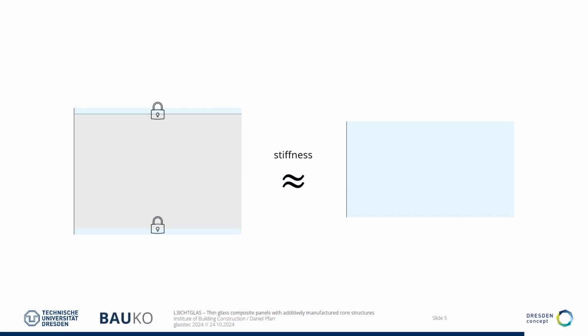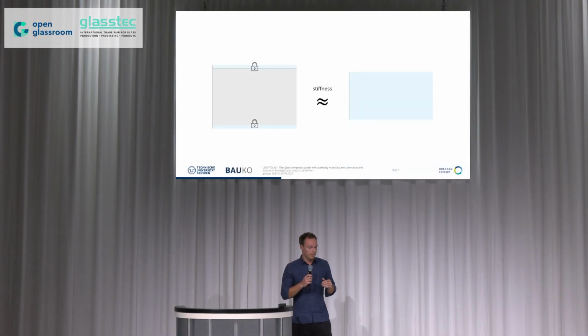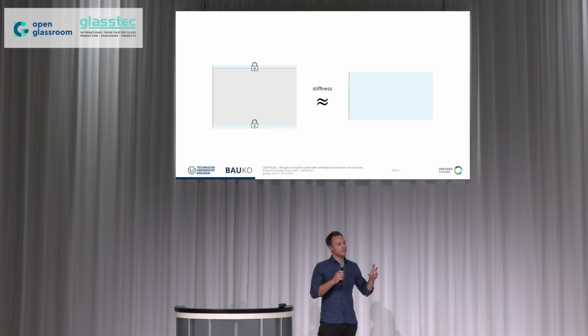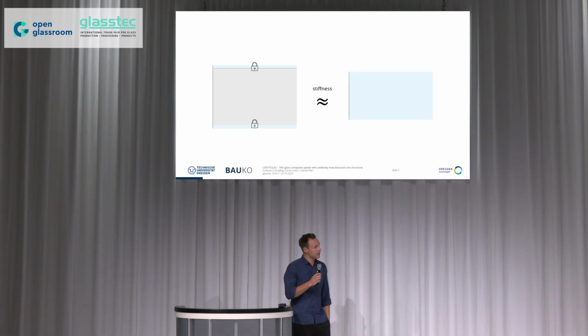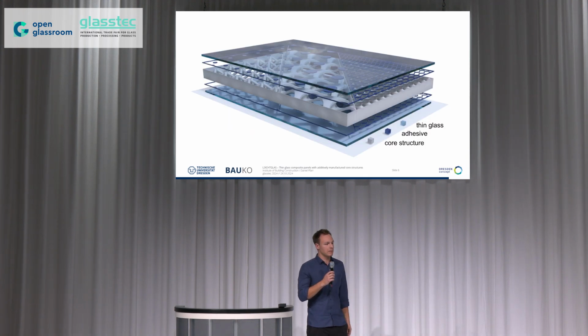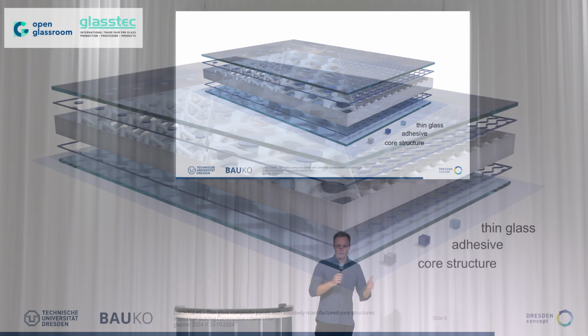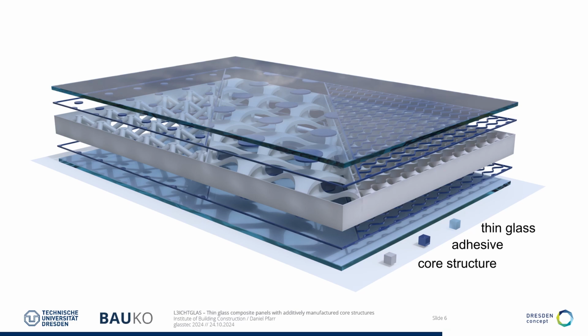And this could be one possible solution, the sandwich theory. So we can divide two thin sheets of glass with some kind of core structure or core topology. And by doing that, we increase the overall stiffness of the panel. So with kind of this composite, we would reach the stiffness of about a 15 millimeter solid block. And that is a rendering of our concept behind it.